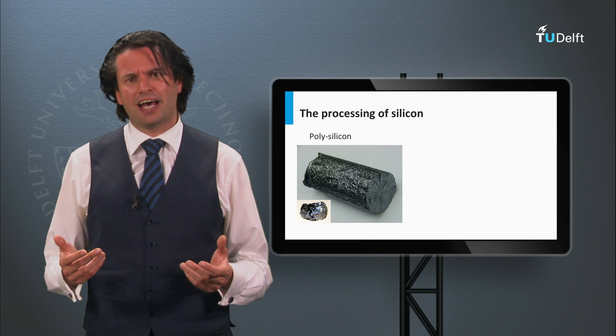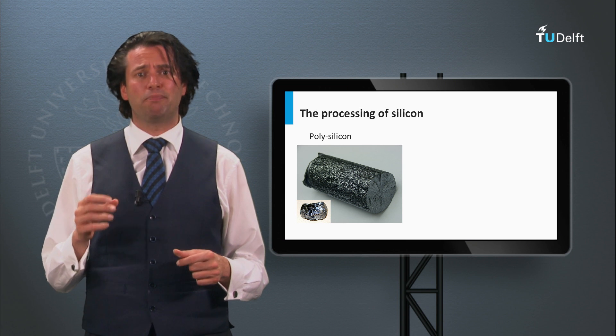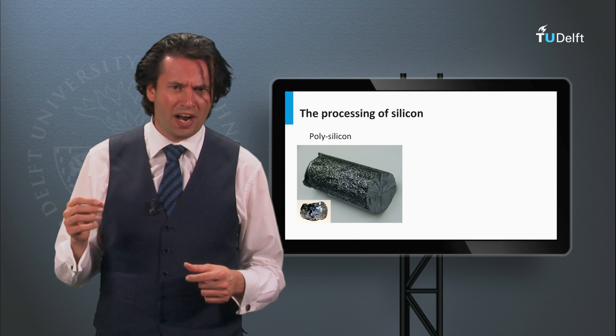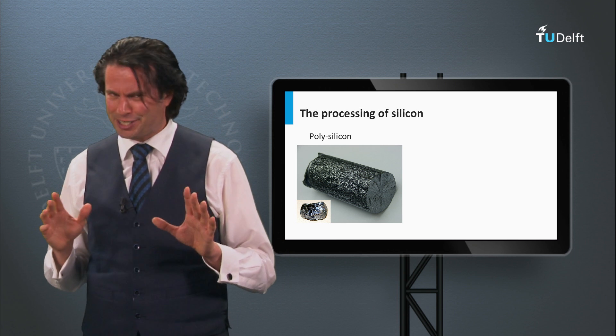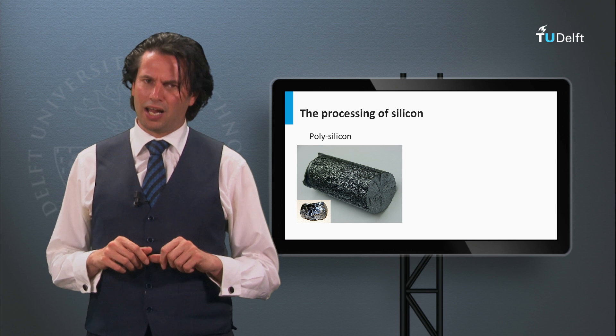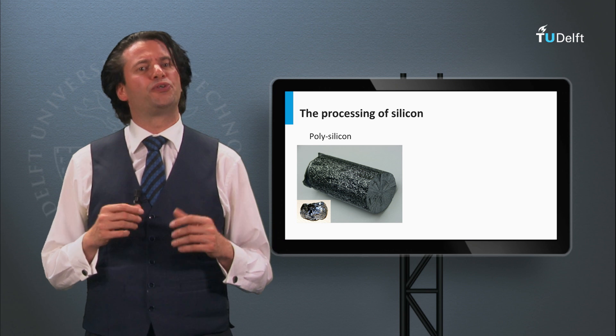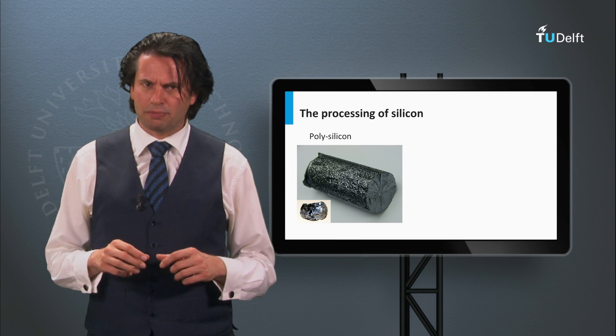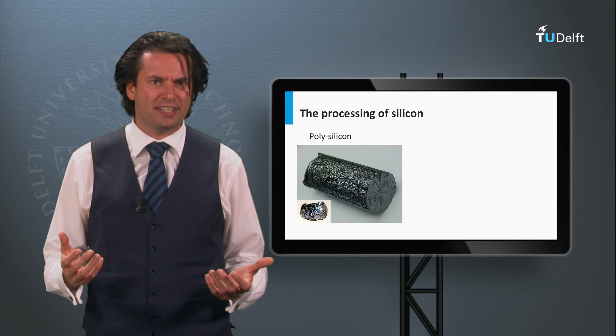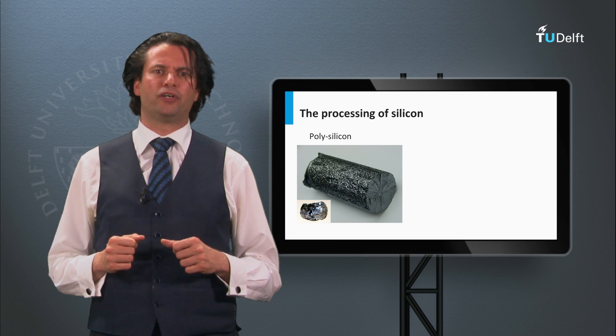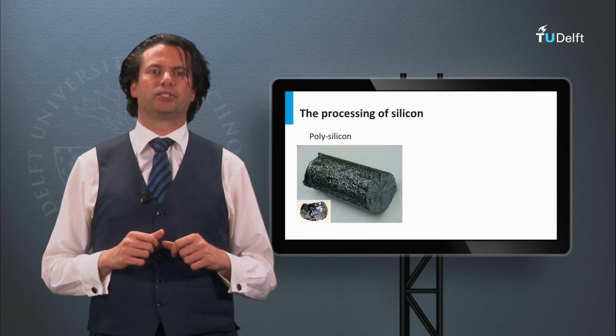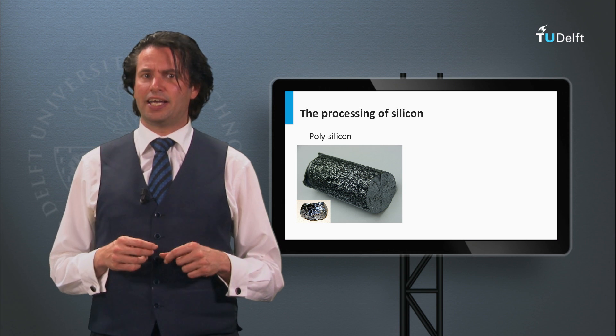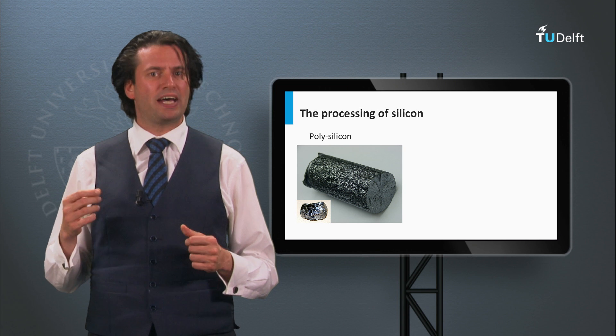Polycrystalline silicon can have a purity as high as 99.9999%, meaning 1 out of 1 million atoms is not a silicon atom. An alternative approach is upgraded metallurgical silicon, where metallurgical silicon is chemically refined by blowing gases through the silicon melt to remove impurities. Although this processing is cheap, the purity is not as high as the Siemens or fluidized bed reactor approaches.